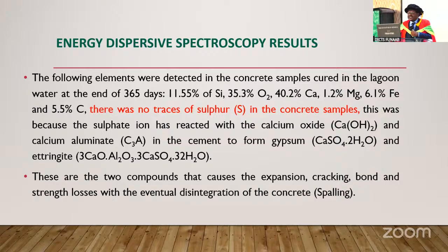The following elements were detected in the concrete sample cured in lagoon water at the end of 365 days: 11.55% of silicon, 35.3% of oxygen, 40.2% of calcium, 1.2% of magnesium, 6.1% of iron, and 5.5% of carbon. There were no traces of sulfur in the concrete sample at the end of 365 days. This was because the sulfate ion had reacted with the calcium oxide and the calcium aluminate in the cement to form gypsum and ettringite. These two compounds, gypsum and ettringite, are the ones that cause the expansion, cracking, bond and strength losses with the eventual disintegration of the concrete. We call this spalling.